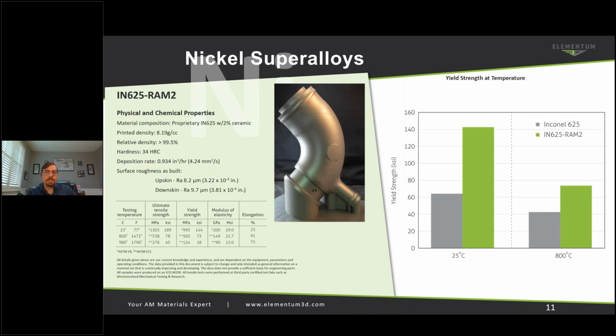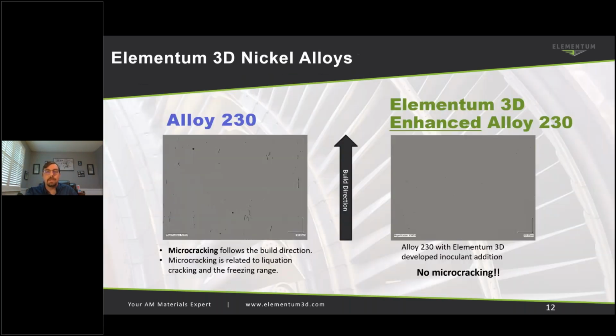I won't go too far into each one of these that I have, but suffice to say, if you look at the properties, we're getting double the yield strength by adding 2% ceramic. We're also getting the same yield strength in the XY as we are the vertical, and it's because of these kind of particulates. So I want this to sink in: whatever nickel superalloy you're looking at, there's potential benefit. You can get better strengths, you can get better high temperature strengths, you can still maintain ductilities with this particular technique that we're doing to a lot of different alloys.